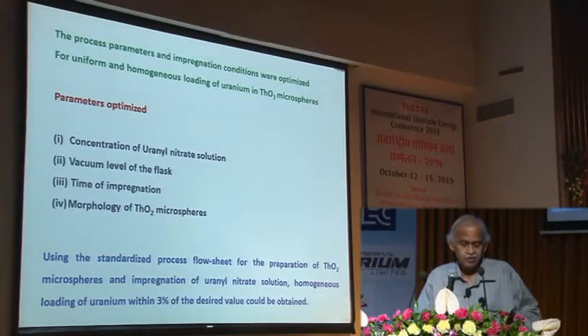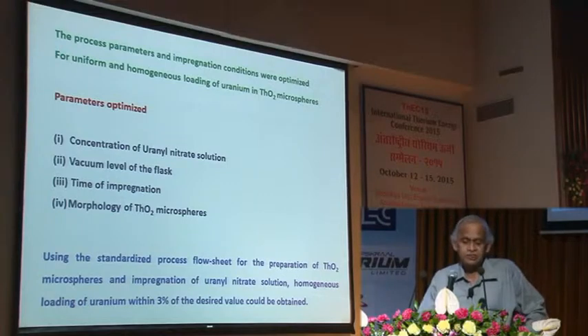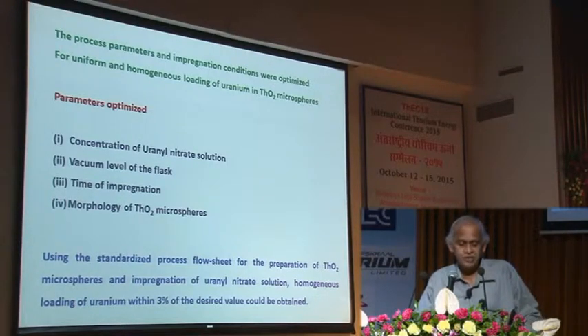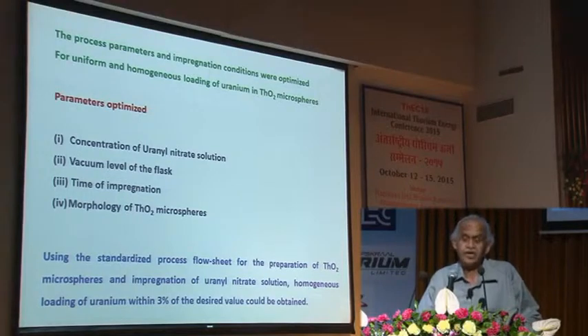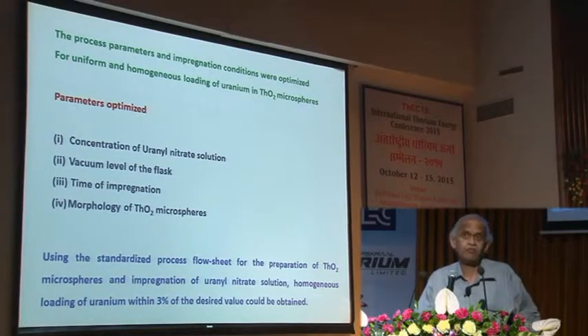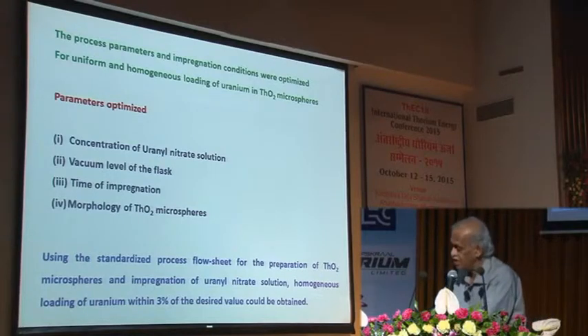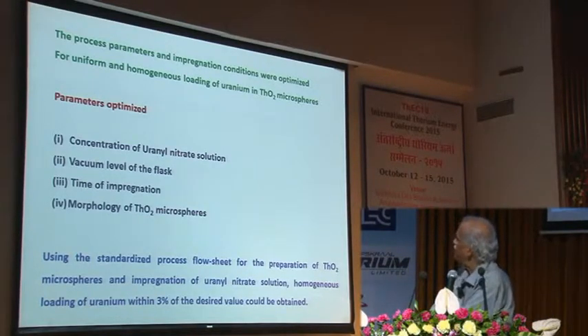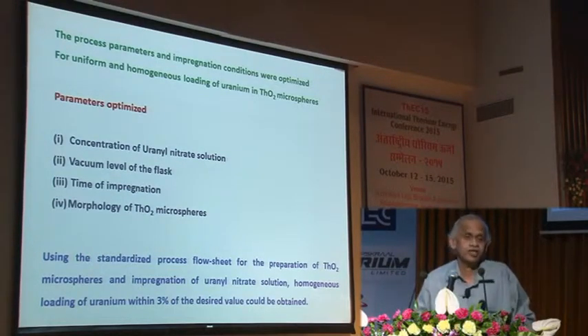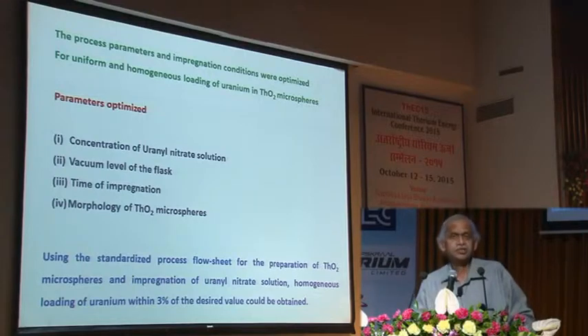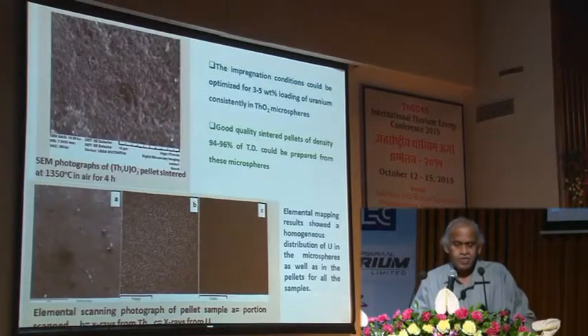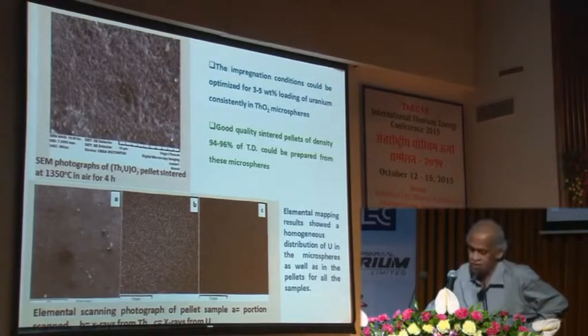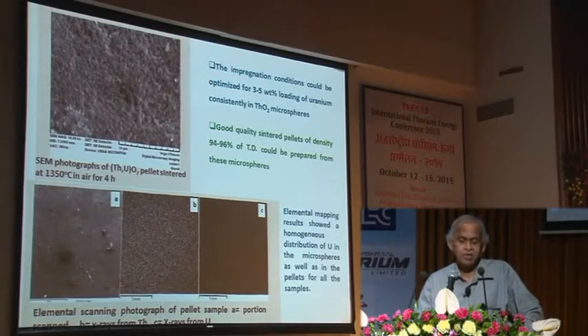uranium shell. As of now we do only simulated, and the process has been optimized for uniform and homogeneous loading of uranium microspheres. We have optimized many of the parameters as indicated here, namely the concentration of uranyl nitrate solution, vacuum level of the system, time of impregnation, and of course morphology of thorium oxide microspheres. Using these optimized parameters, a flow sheet has been standardized, and the results that are obtained are shown in the form of SEM photographs.